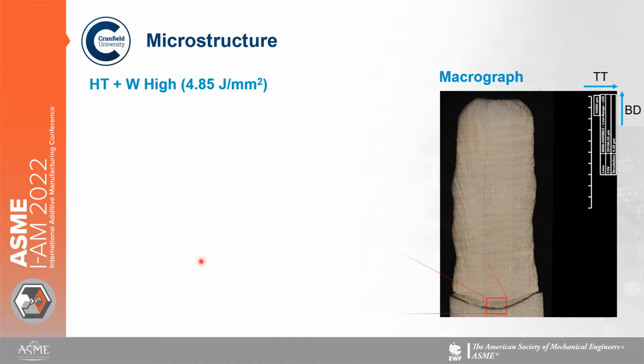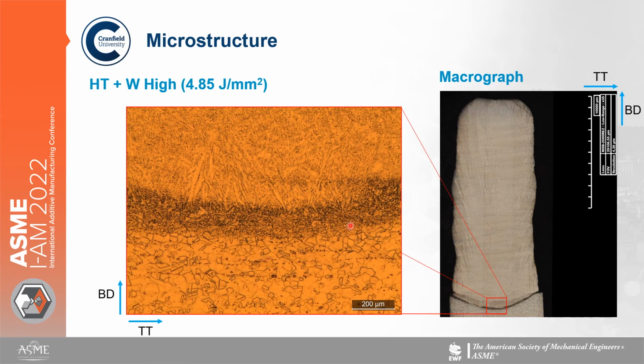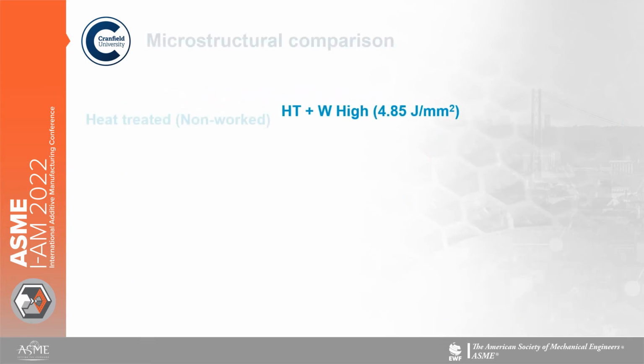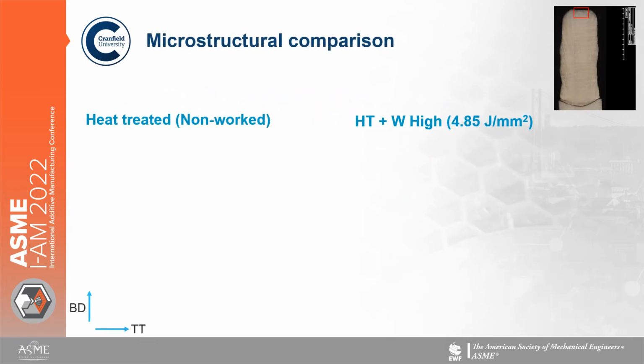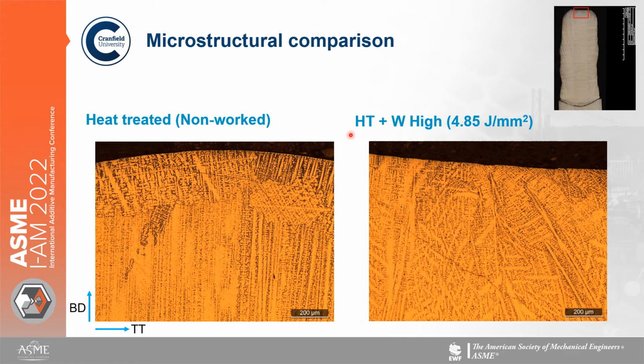And if we look at the bottom of the sample, again you can see our remelt line here, showing a bit more of an indentation than what it was before, as well as the grain structure. So if we compare the two and look at the top of both of the samples together, you can see the clear difference between them in the different texture of the dendrites and the disruption that the peening process has caused.